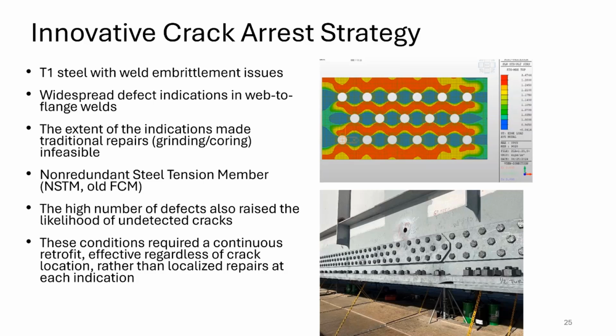The concern is basically that if you were to get a full fracture in the member, a full section fracture, that might lead to collapse of the structure. And this led to the development of a repair that was a continuous retrofit that had to be effective regardless of the actual location of the crack or any hypothetical location.